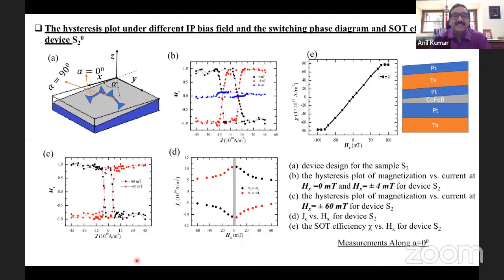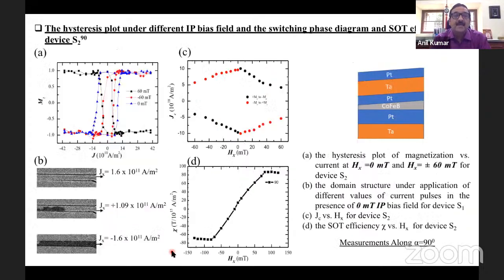Now I go to the next structure, which is perpendicular to the thickness gradient direction. Here you suddenly see that even without applying a magnetic field, I'm able to switch the magnetization by applying pure electrical current from plus M state to minus M state. And also now if you look at the switching phase diagram, there is no gray area here, and even at zero field, I'm able to switch the magnetization. Now I have come to a situation where just by applying electrical current, because of a small thickness gradient, I am able to switch the magnetization.